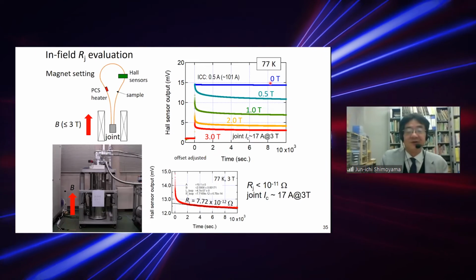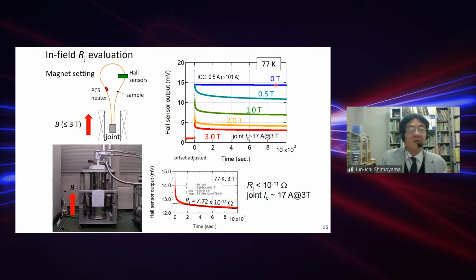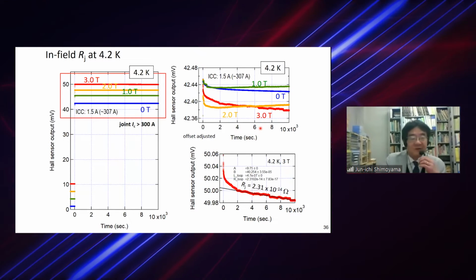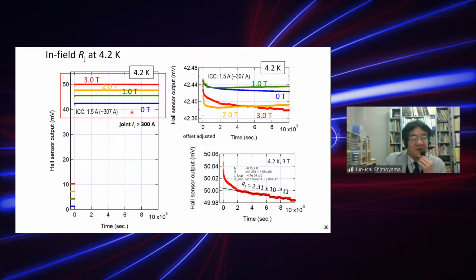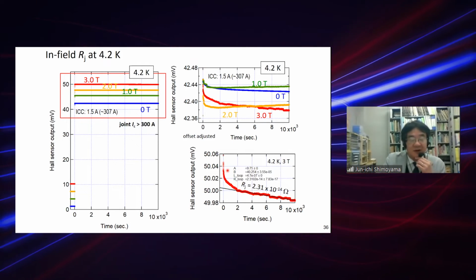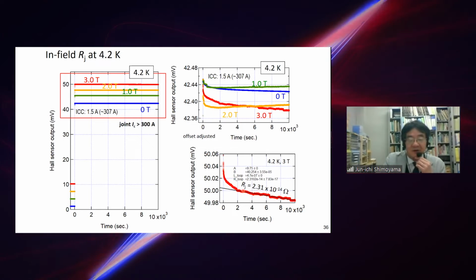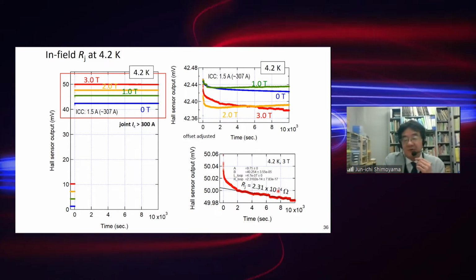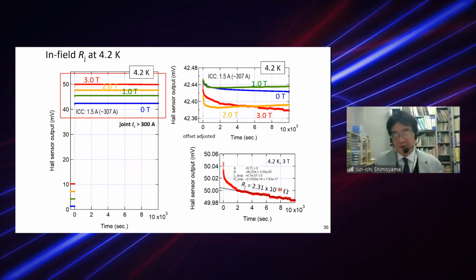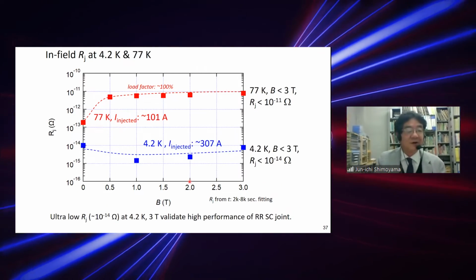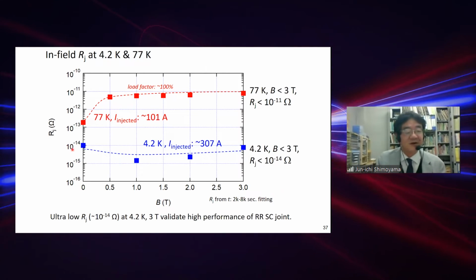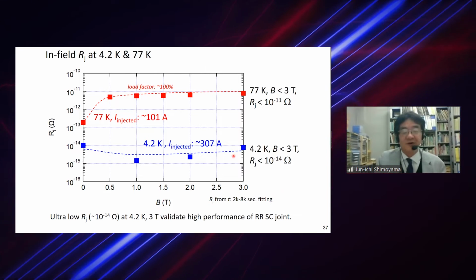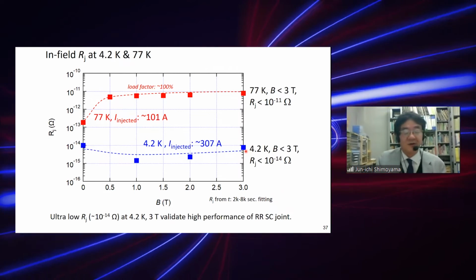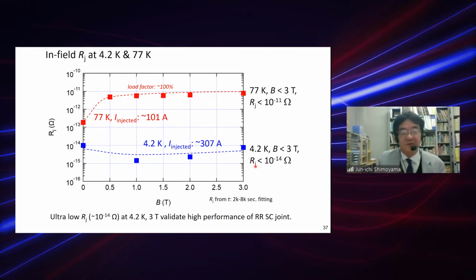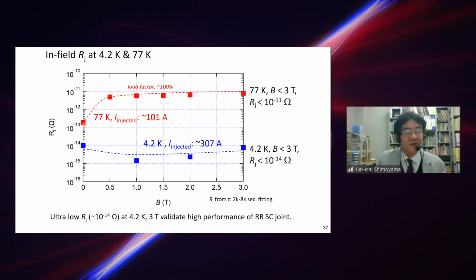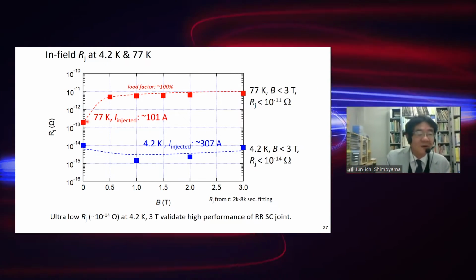Only at 0 Tesla can we observe very slow current decay, while at 4.2 Kelvin, even at 3 Tesla, this joint can carry large current without showing large decrease in current. As you see here, the calculated joint resistance is on the order of 10 to minus 14 ohms, very low. This is completely a superconducting joint. This is a summarized result for the superconducting joint resistance, as you see here. At 4.2 Kelvin, up to 3 Tesla, we can flow large current without decay of the current through the superconducting joint. At 77 Kelvin, only at low field can we expect a persistent current circuit.